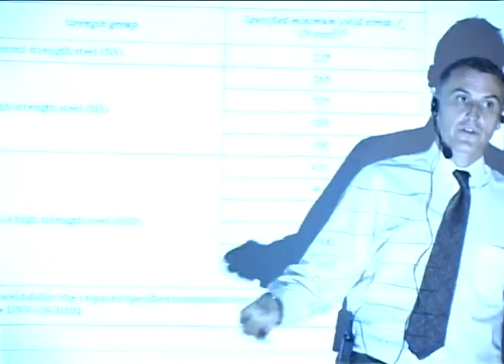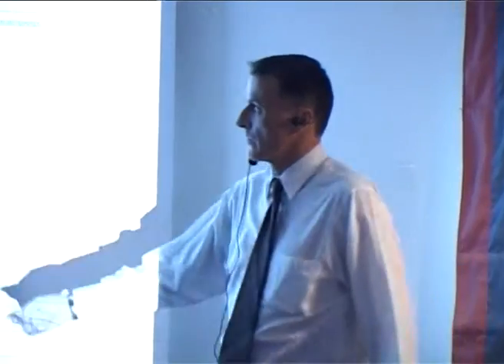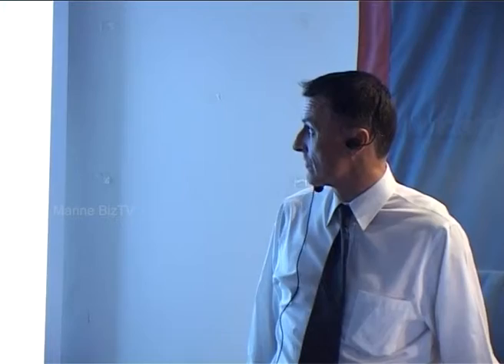These are DNV grades of plate. The higher the number, the harder it is to weld — that's the important thing for you. When you start getting three-digit numbers, 500s, 690s, you are talking difficult plate to weld. When you're up here, this is ship plate, A-grade plate. It's much more forgiving — it will let you weld relatively easily. This stuff here is not forgiving at all. You'll only really see it on some big offshore projects, but when you see the big numbers, you need to be aware that something special is going on.